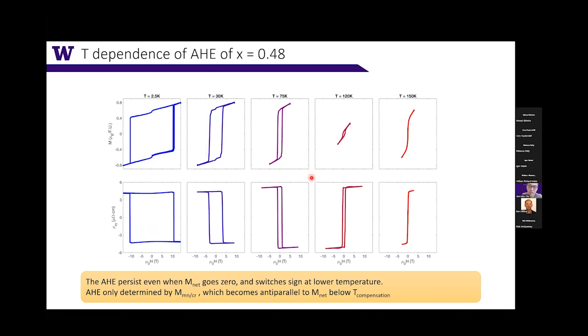What this is telling us is that the anomalous Hall doesn't really care about the net magnetization. It is actually following the magnetization of the manganese. At high temperature, when the manganese moment dominates, the field is always parallel to the manganese moments, so you have a positive sign of the anomalous Hall coefficient. However, at low temperature, when the magnetization reversal happens, the manganese moment is antiparallel to the field, so you have a negative anomalous Hall coefficient.